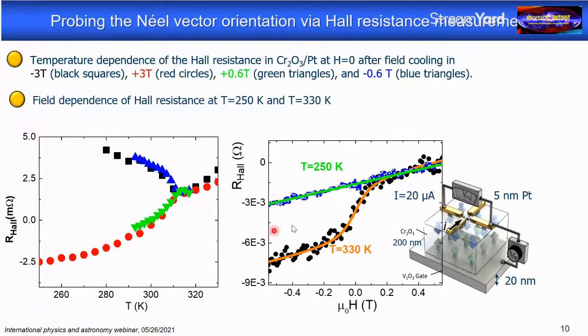Here you see measurements as a function of magnetic field at different temperatures, below and above and nearby the antiferromagnetic ordering temperature. And note that below the antiferromagnetic ordering temperature, the field dependence is linear and rather weak. And only above and near the ordering temperature of the chromium oxide, you get these S-shaped curves here. That is something that also becomes important in a minute.